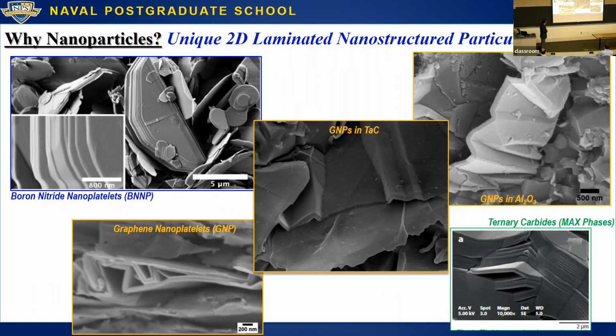These are different nanostructures that I've worked with. These are all my images. We've become very interested in two-dimensional nanoparticles as well. Some of the same ideas apply. You've got a very high surface area phase, good for transferring load. You have very good in-plane mechanical properties. And just like in the case of the multi-wall carbon nanotubes, you develop some interesting mechanisms when you actually stack some of these layers. And usually, if you're talking about individual layers, let's say graphene, for example, you still want to have something no more than maybe 20 to 30 layers.